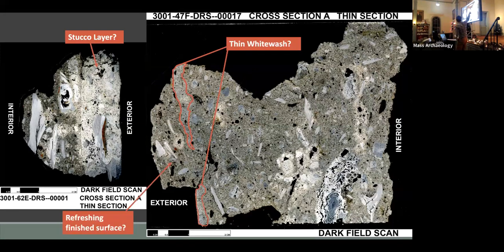And these lighter areas here, these streaks, are the mottled texture binder that I also mentioned. It's a little more obvious in some samples, but something that I want to point out is that under the microscope, this stucco layer does not appear the same as these mottled texture areas. So even though the color may be similar, that doesn't necessarily mean that chemically or mineralogically these are the same material, or that the same processes are happening to these parts of the tabby daub.